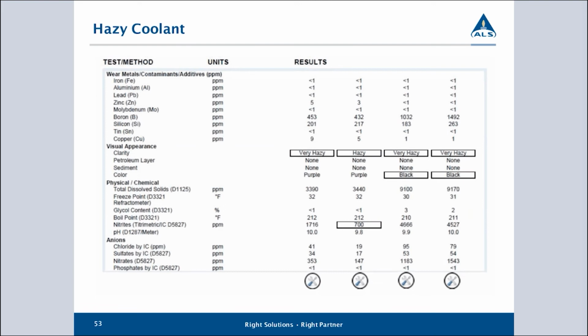When you see this, my recommendation is we need to drain and try and flush the system. So we want to drain the coolant, fill it up with clean water, and run it for a few minutes to try and pick up any dissolved salts we can, try and resolubilize it back into the water. Then drain that water, and refill with proper coolant again to see if we can clear this material out.